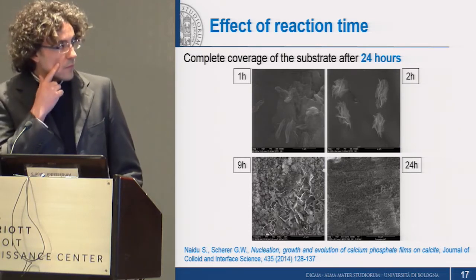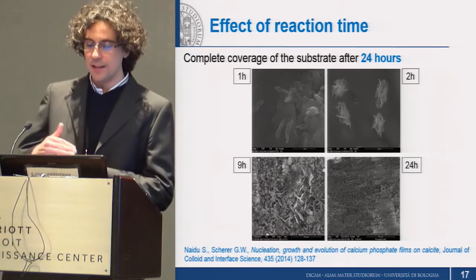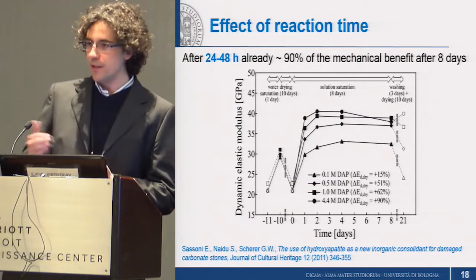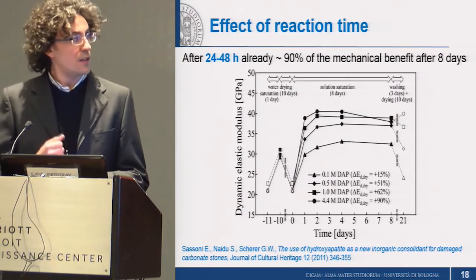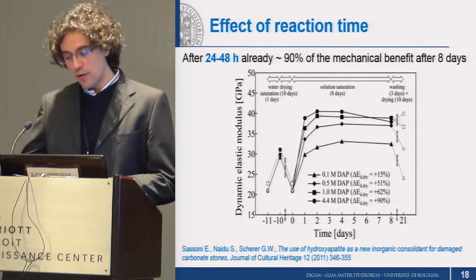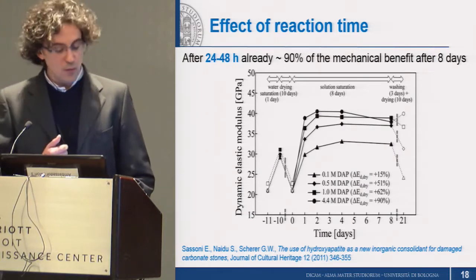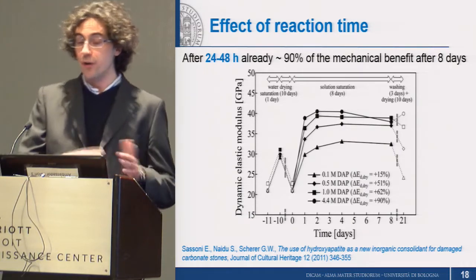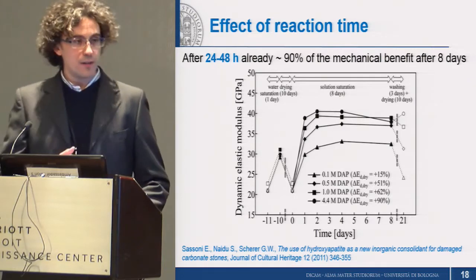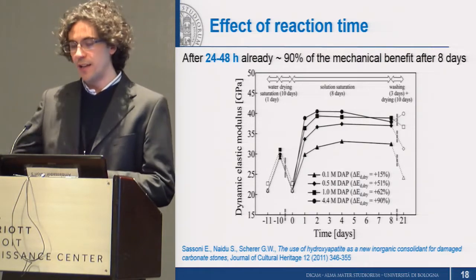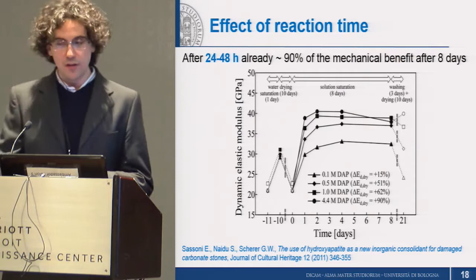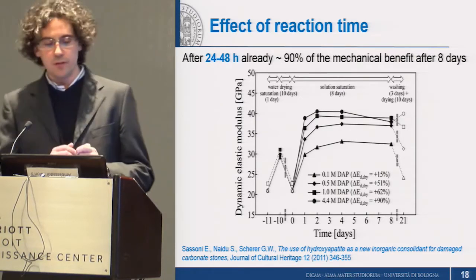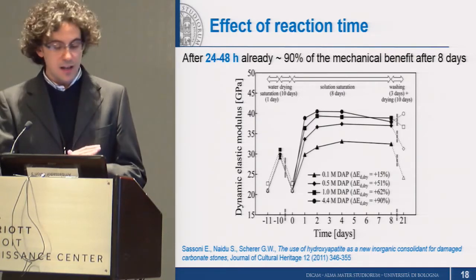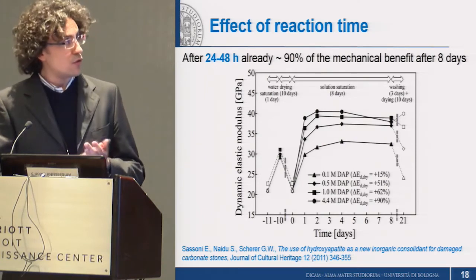So we also checked the development of mechanical properties in terms of consolidating ability, so its progress over time, and as you can see, we found that basically after 48 hours, the mechanical improvement is already 90% of the one that we get after 8 days. So this 24 hours was identified as the ideal treatment duration.